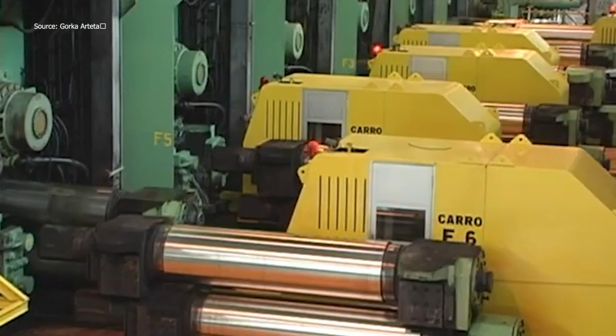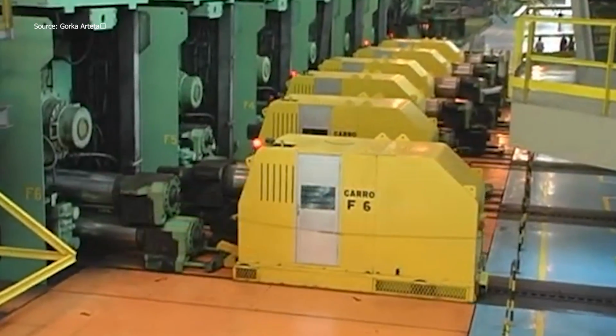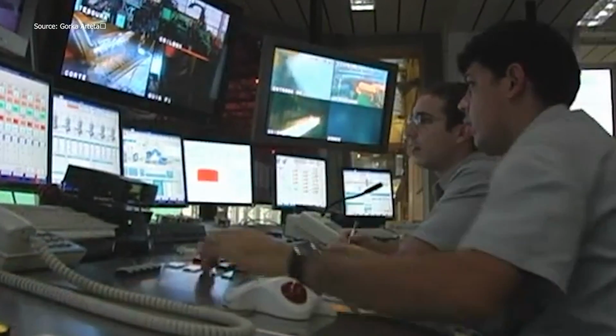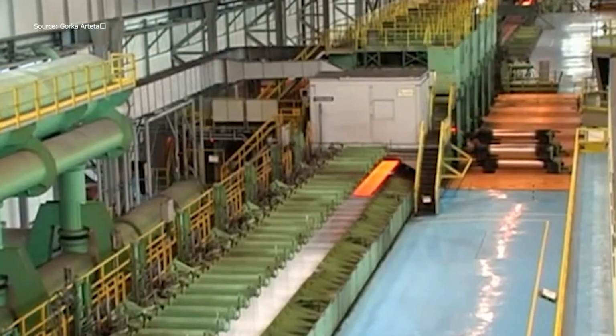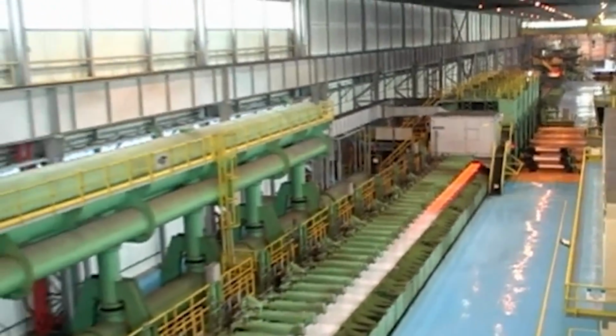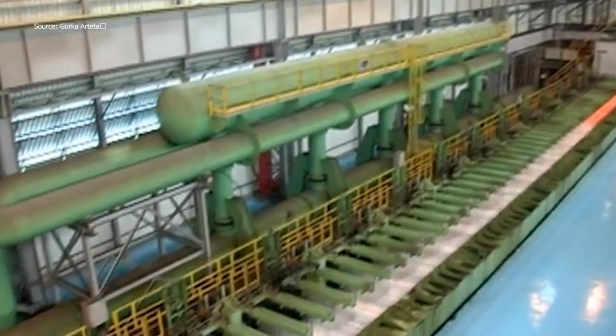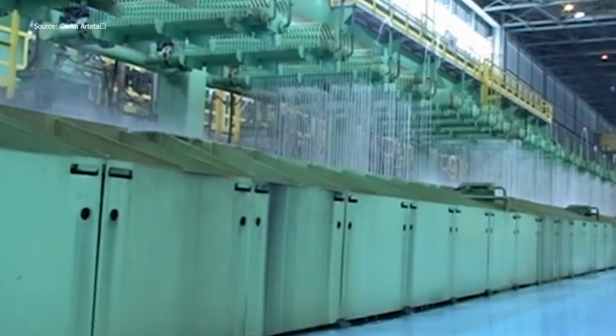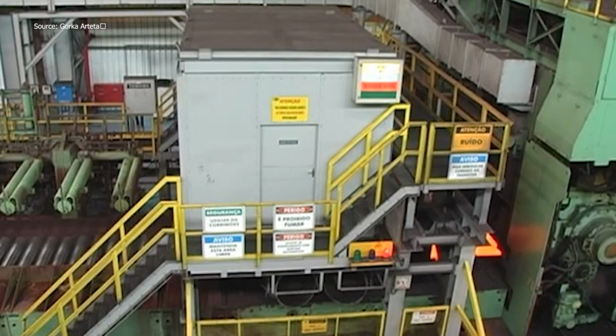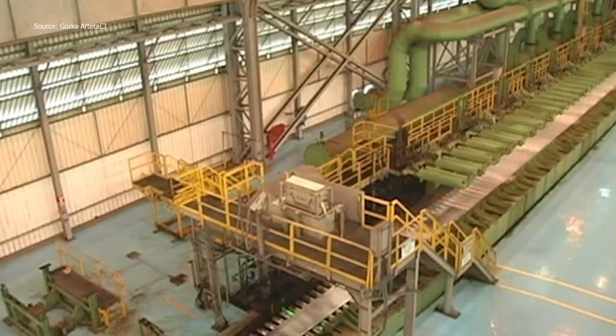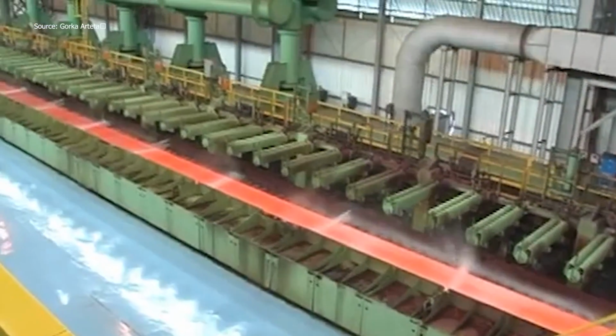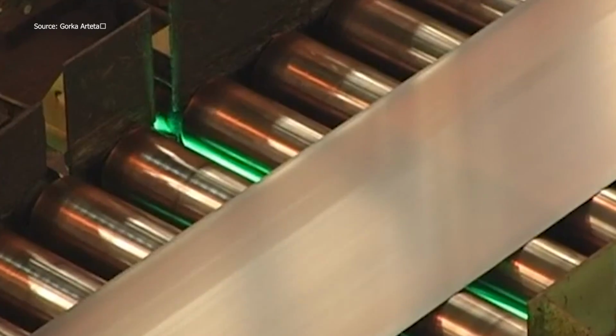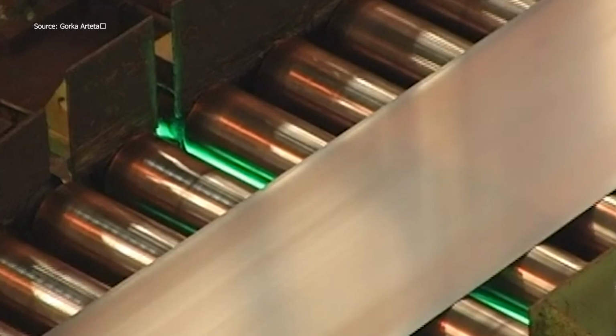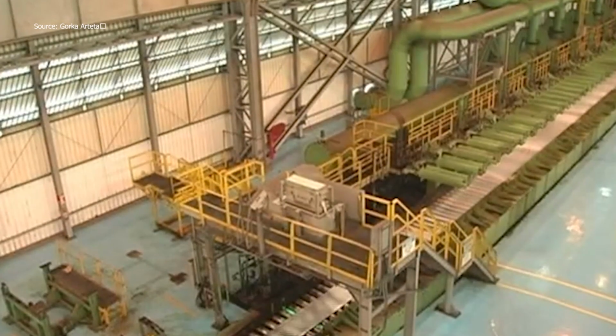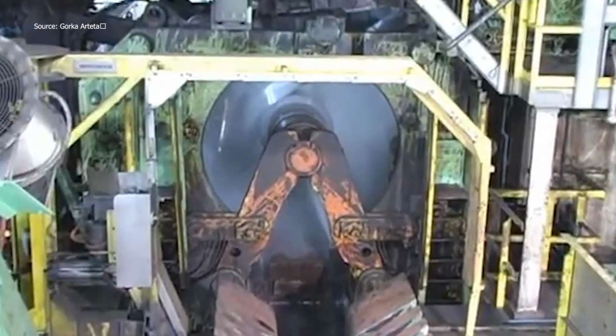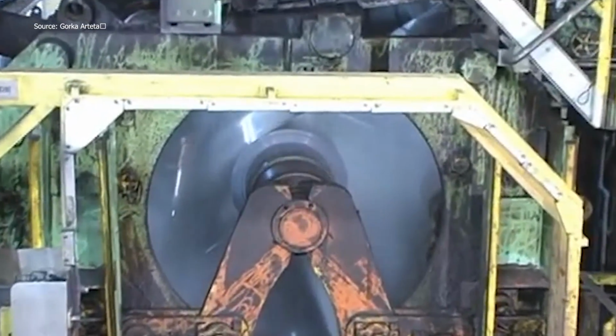After uncoiling, blanks are cut and sent through finishing mills with 6 rolling stands that bring thickness down to 1.2 to 16 millimeters. The strips are then cooled on a laminar bed and inspected by cameras detecting surface defects in real time. Hydraulic coil winders finish the process by coiling the strips, which are strapped, weighed, and transported to the cooling yard. The coils either proceed to finishing lines for cutting and edging, or are prepared for shipment. This tightly controlled process blends heat, force, and precision, producing steel coils vital for modern industries worldwide.